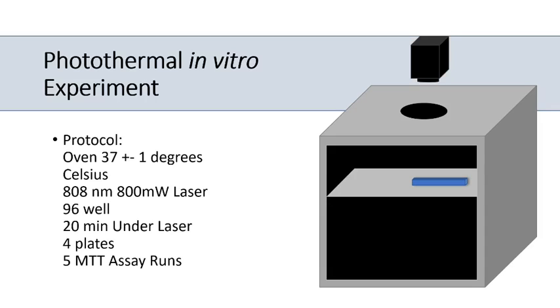So we kept the oven at 37 degrees Celsius. Again, that's human body temperature, so that's why we're looking for that 37 degrees. We use the 808 nanometer laser, and it's an 800 milliwatt laser. If you'll recall, I mentioned that near infrared is not harmful at low power densities. The standard that is supposed to be healthy is about 1 watt per centimeter squared. Our laser is about 2 watts per centimeter squared. But what we're seeing in the research right now is much, much higher power densities, sometimes even as high as 15 watts per centimeter squared. So we're much closer to a healthy range in our experiments.